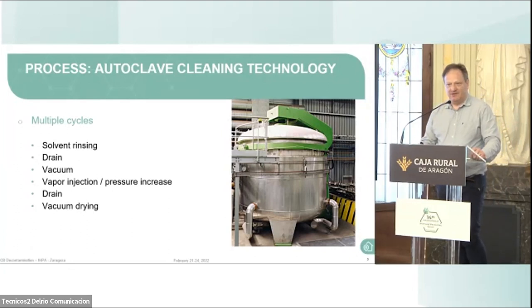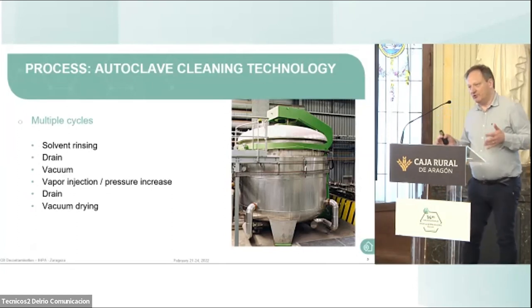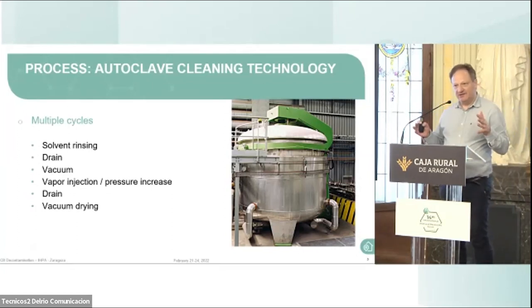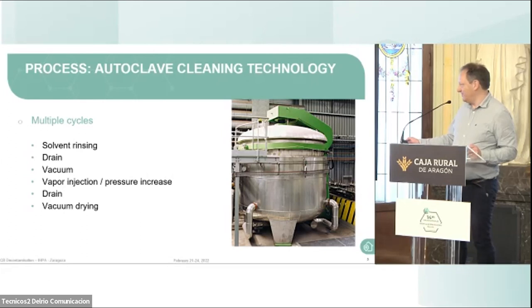This system works fine. It's a surface cleaning. This means everything is cleaned, but the surface needs to be accessible. This means the core of the transformer, you have to dismantle it because it's packed material, and you have to open the material and then put it in the machine, and then you are sure that it's fully cleaned. This system is a cleaning system for metals. It doesn't like anything porous, and the porous material in a transformer gives several problems, mainly for the drying. When there is a lot of paper or wood inside, we need much longer drying times than a standard metal degreasing machine. I come back to the porous material because this is a real problem.